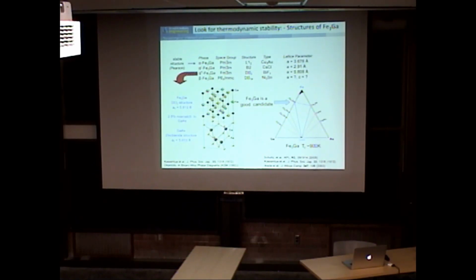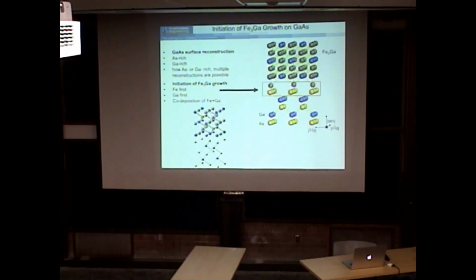But if you look at some of the high temperature phases, there's this Fe3Ga, which is this DO3 structure, which you can think of as a Heusler, Fe2 iron gallium. If I look at that, the mismatch to gallium arsenide is something like 2.8%. Could we stabilize this on top of the gallium arsenide? And does it work? And it's got a Curie temperature of about 900 K.